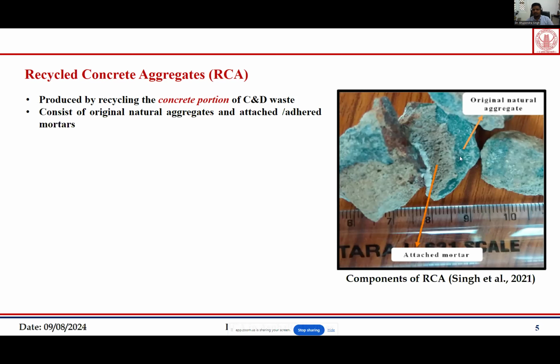and then there is a layer of adhered mortar, which is because it was part of concrete, so there will be some mortar which is still attached to those aggregates, and that is what you will find in any recycled concrete aggregate. Now people have used this recycled concrete aggregate in the unbound pavement layers also, cement concrete and bituminous concrete also.